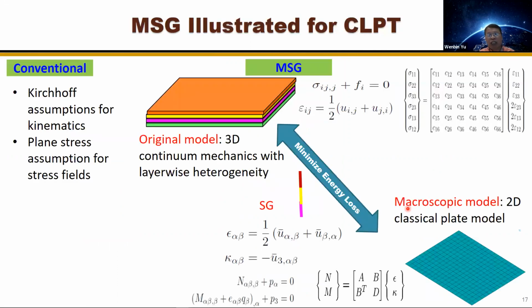For example, I still use the same problem, a stack of laminates. Now I know that if I treat it as black aluminum, I cannot take care of the flexure property, well, the bending. So what I do, I want a plate model. Your starting model is the 3D elasticity model with layer-wise heterogeneity. Your end model is a two-dimensional classical plate model. And your structure gene is still the transverse normal. And you can minimize the information loss. At the end of the day, you will derive this model with the